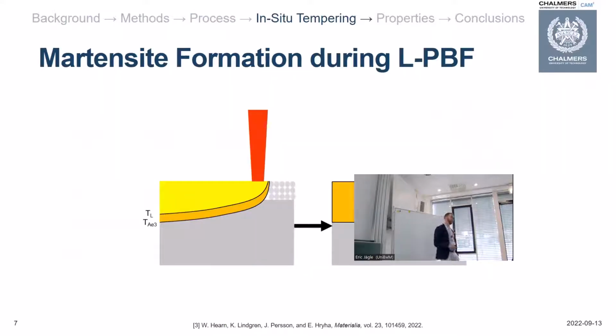But before we can talk about in-situ tempering, we have to understand what's the initial state of martensite in this material during the process. Generally, the martensite that first forms will happen during layer melting. Of course, as you usually would do, you have your laser scanning across your powder bed. Everything heated above the liquidus temperature forms a liquid melt pool. Pretty straightforward. But since this material is dominated by the solid state transformation of martensite, the important aspect is looking at the portion of material that's heated above your austenite stability temperature, as this will first form austenite, then rapidly cool and form your untempered martensite.